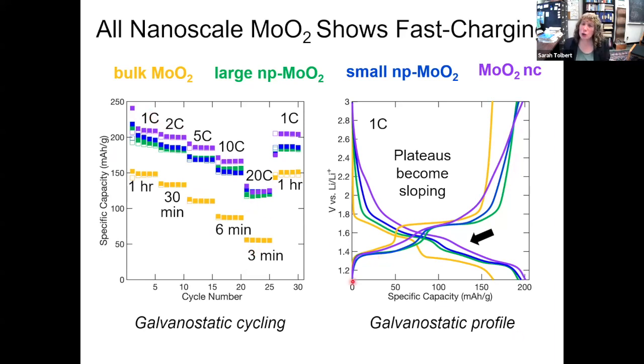If we look at the actual current voltage curve, we see something else that tells us about phase transitions. If we look at the bulk, we see this plateau. What that means is as we put in more current, the voltage is not changing. This is just like ice in water. If you have a solution of ice and water and you're trying to melt it, as long as ice and water are present, it is locked at 0 degrees C. Once you've melted all the ice, it can heat up. But when you have two phases present, you lock the temperature.